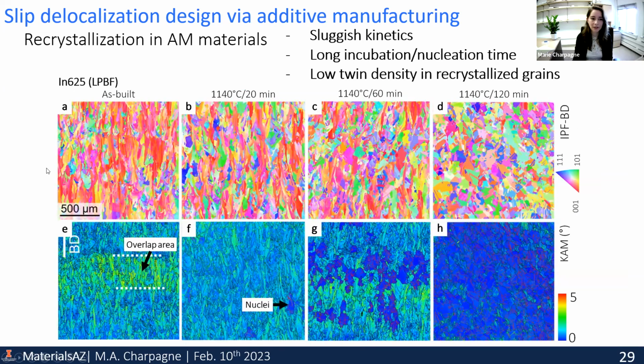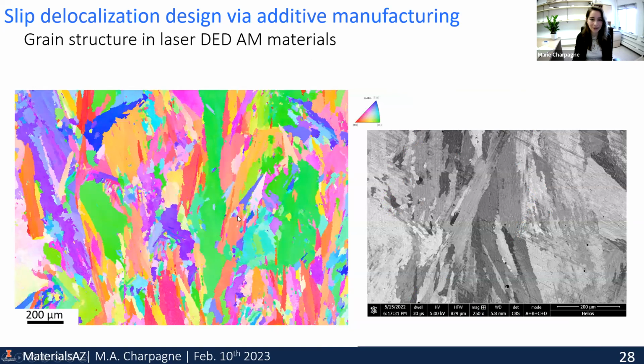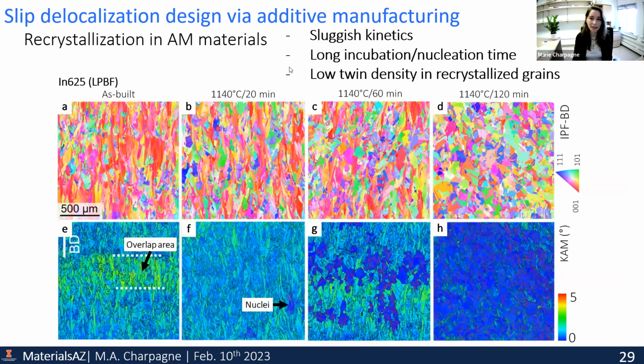And so I also mentioned that those materials have, of course, no twin density, but as you can see, the grain size is very high in this previous micrograph. And so what we need to work on is techniques to refine it. A natural thing that can come to mind is static recrystallization after printing. And there is very, very little fundamental understanding as to how recrystallization happens in those materials. In practice, there are just a handful of articles that were published, but people report very sluggish kinetics, a long incubation time, and a nucleation delay that's also very long, and also a low twin density and a low density overall of nuclei. So this is illustrated in this preliminary data here again, where this is in Inconel 625.